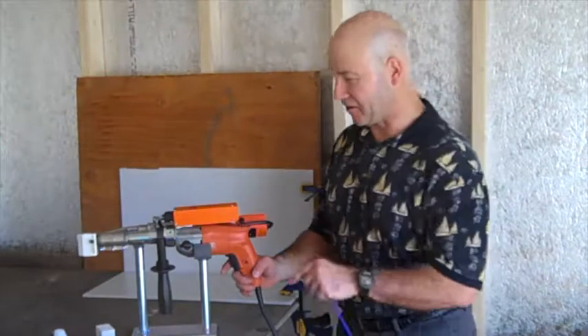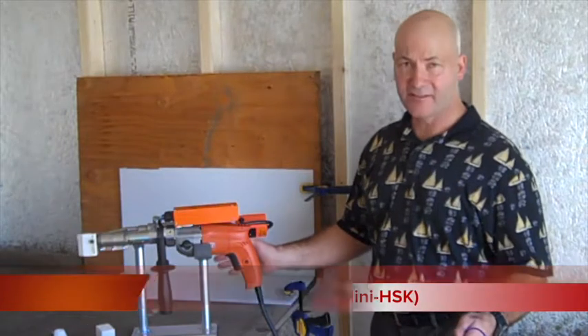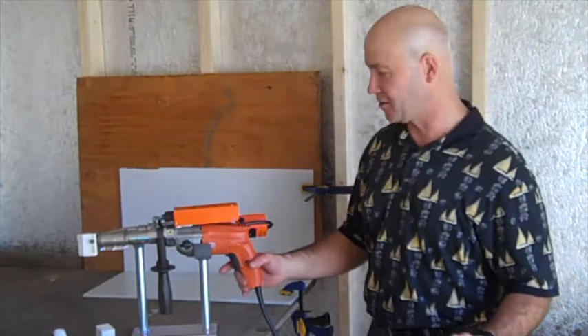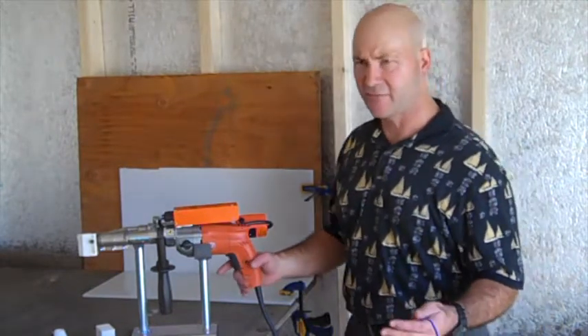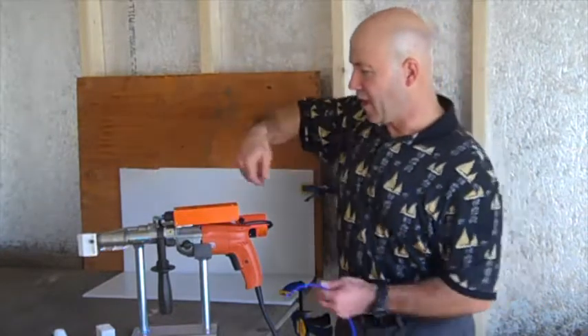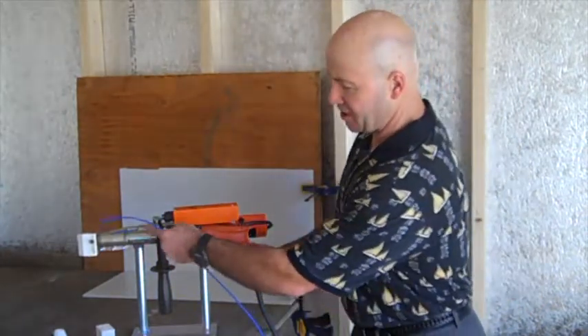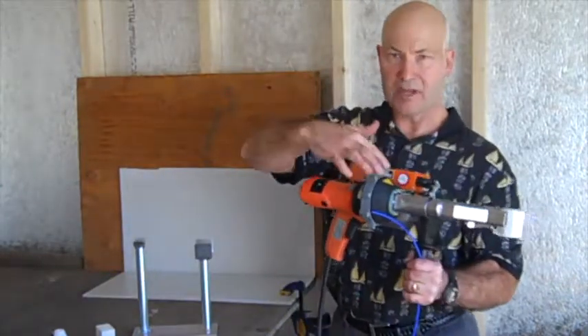We've now warmed this up so there's a certain temperature for my HDPE. I know that I've got a set temperature I need to meet, which is in this case 265 degrees Celsius, or I think it's 570 Fahrenheit. So I've set my temperature reading here so I've got my extruders heating up here and over here I've got a preheater.